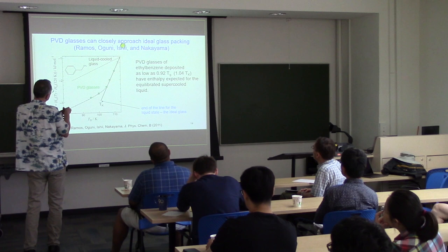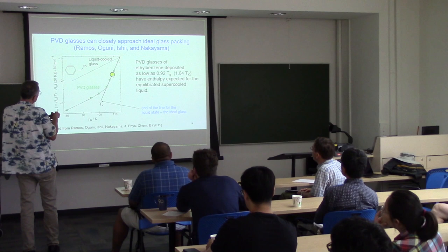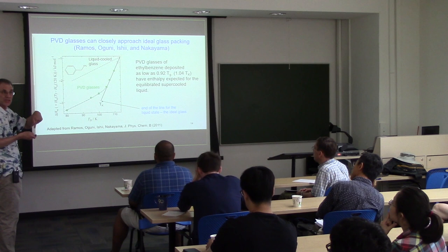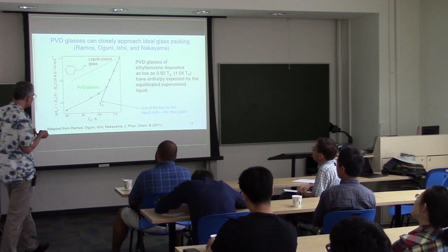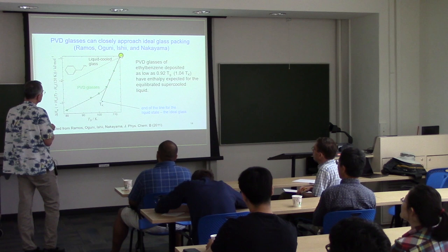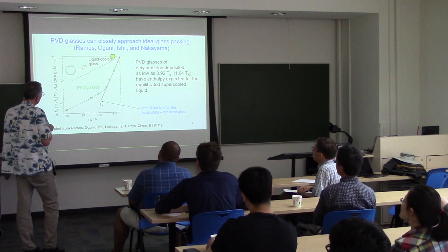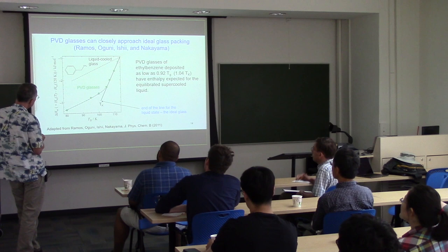This shows that one of the cool things about vapor deposition is that you can apparently equilibrate the system down to much lower temperatures than you can from liquid cooling. In this case, you move about 2/3 of the way down to the Kauzmann temperature. I would interpret this result to indicate that this extrapolation, which Dane was worried about, why should it be a line, why should it be any simple function? Well, it looks pretty simple, at least for closing 2/3 of that gap. So I would say this experiment and other experiments like it are suggestive. They don't prove it, but they're suggestive